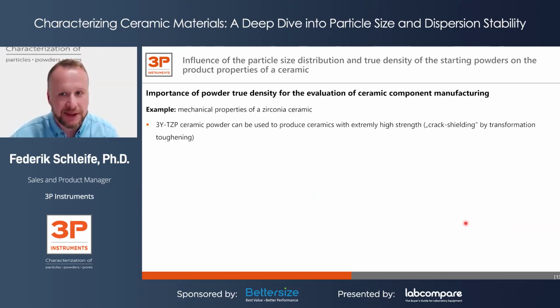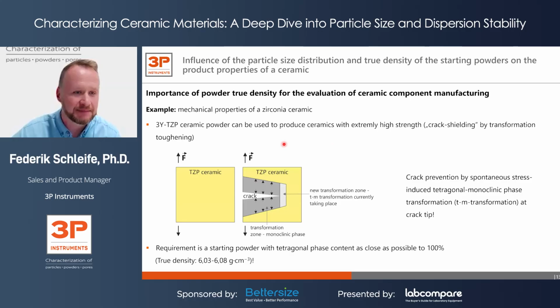So what is a typical application for this tetragonal structure, and why might this be the one you want to have? Those stabilized ceramic powders can be used to produce ceramics with extremely high strength. Why? Because there's an effect called crack shielding by transformation toughening. And what's that? If you apply an external force on such a tetragonal zirconia ceramic workpiece, this leads to a crack. The following effect prevents the crack from traveling through the entire system.